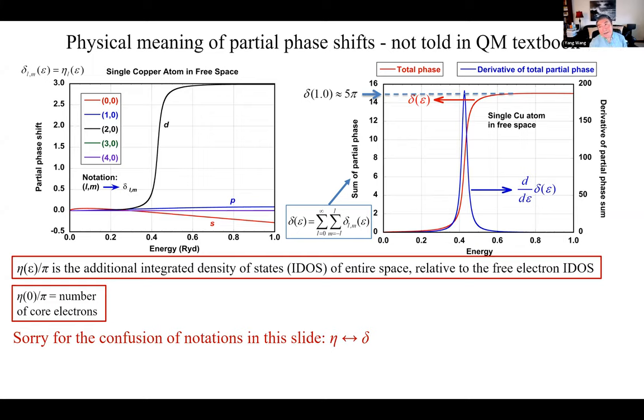But it still depends on the energy level. If the energy level is low enough, you form a core state. It's still a bound state within each atom. For high energy levels, which form the valence, the states are not bound by the local atom; rather, they hybridize with the neighboring atoms. Isn't it true that for core states you don't have delta functions, you really just have very narrow bands? I think you always have bands. You never have really discrete levels, theoretically speaking, except that they're extremely narrow.